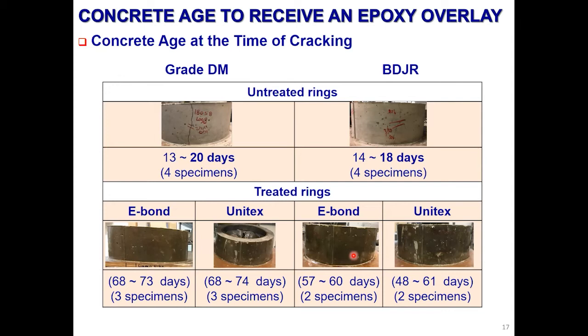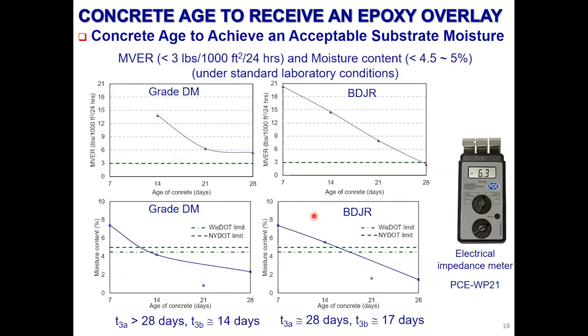Once concrete cracks after overlay application, it will be very hard to inspect and identify. Because of that, we had to wait at least the concrete cracking age to apply overlays. The other parameter is the moisture content. The typical industrial rate for flooring is 3 pounds per 1,000 square feet within 24 hours. It's called the moisture vapor evaporation rate. And then there are some specifications looking at moisture content, which can be less than 4.5 or 5%. We evaluate the moisture content using an electrical impedance meter.